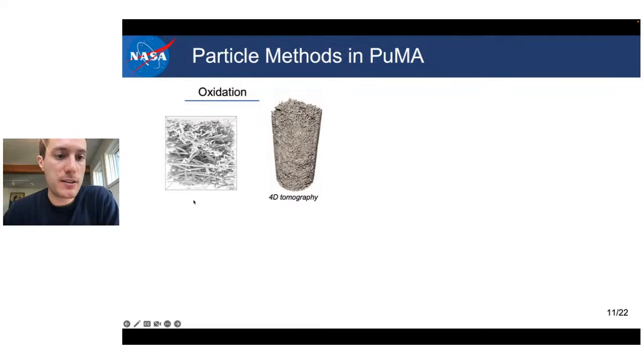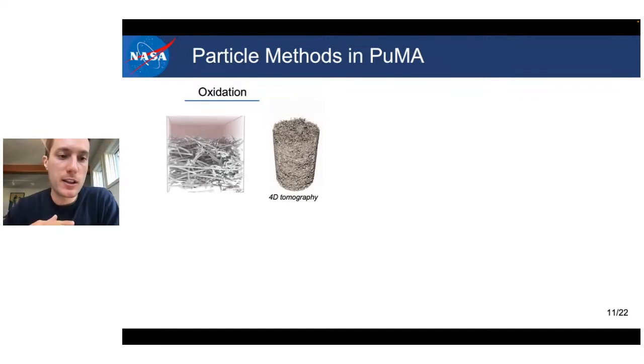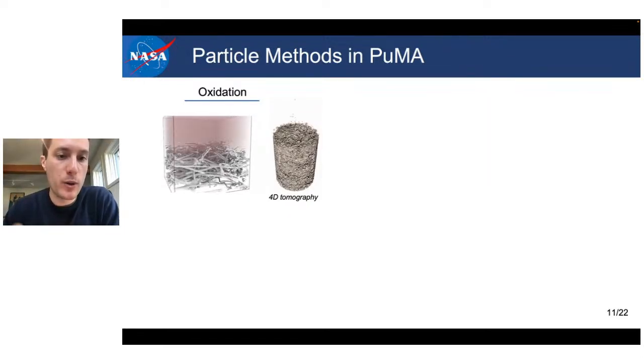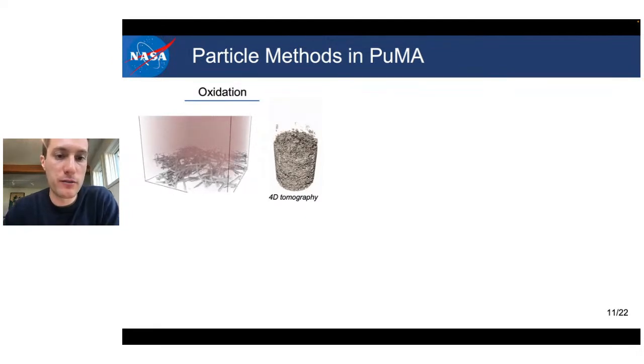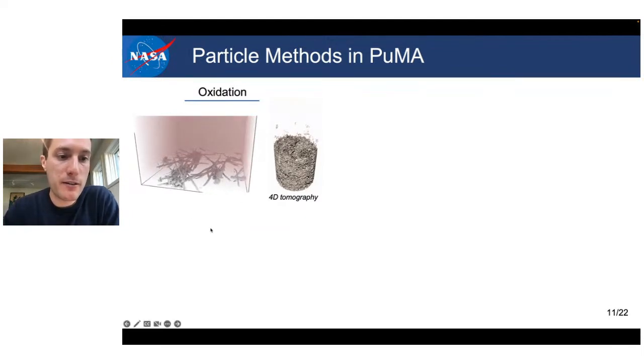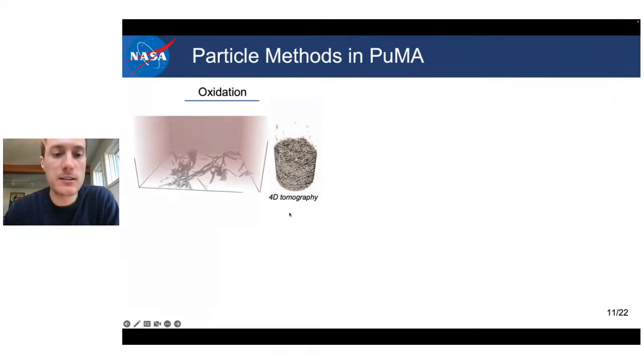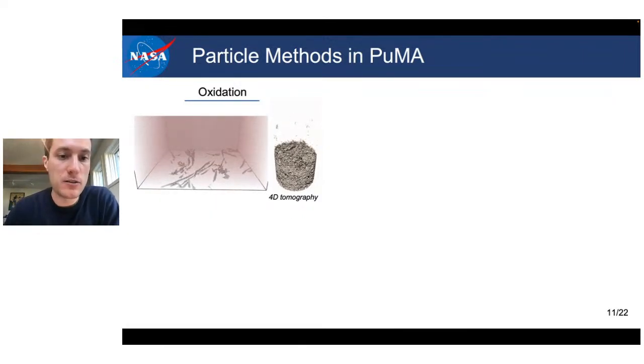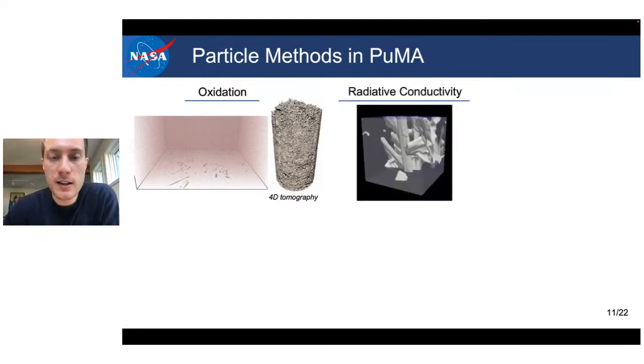And on the left is instead a similar domain in Puma. And we can basically mimic the same type of oxidation of the surface by tweaking the sticking probability of the particles hitting the surface of the model. So again, on the left is a Puma simulation, and on the right is an actual real domain oxidizing on the surface. Then we can also compute the radiative conductivity.